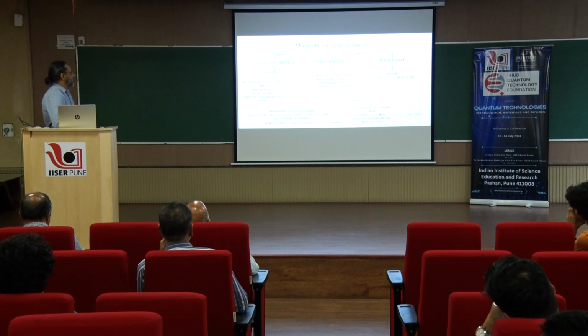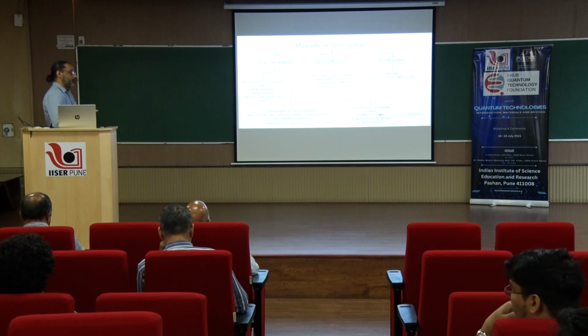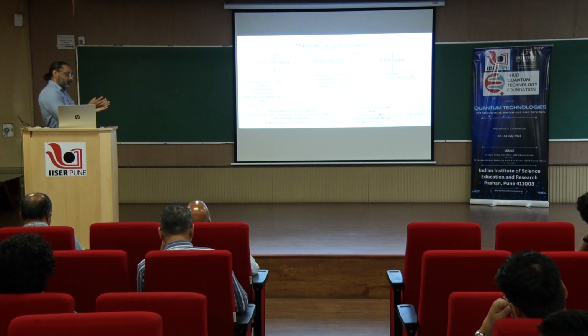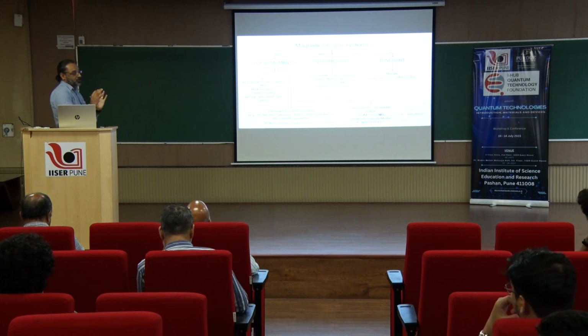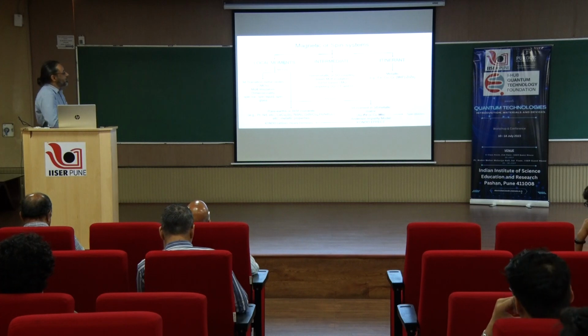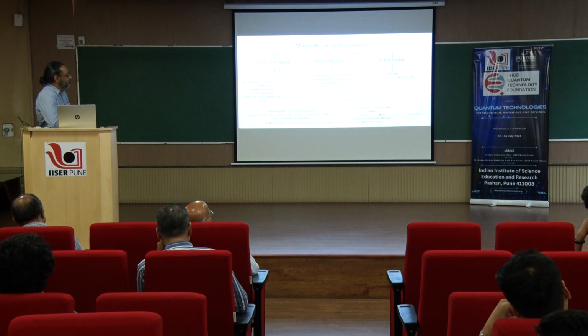And then, as I was telling you, between the itinerant picture where the electrons that give rise to spontaneous magnetization, a part of those electrons is also contributing to the electrical conductivity. So it's a very flux-like situation where, for instance, the d electrons of iron would be partially localized at the iron site.